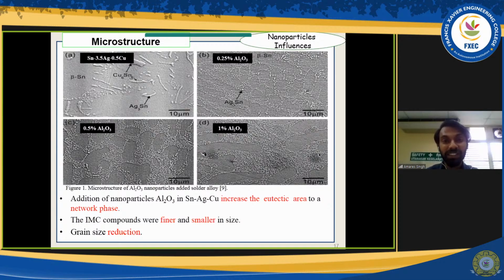So when I say resist deformation, it basically helps us on the hardness properties. This can be only achieved if you are adding small nanoparticles. If you are adding large sized microparticles, you would not produce a eutectic area because these microparticles will not act as a grain size reduction. So we can see in the third bullet, I've said grain size reduction. This grain size reduction happens when the nanoparticles are in small scale.